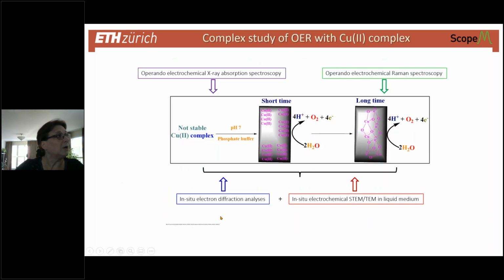So now I have here just an intermediate summary of our study. It was a complex study. We have an unstable copper-2 complex that is added to neutral electrolyte, and after a short time we have a decomposition of the compound, and then over a prolonged period these particles transform into stable copper oxide.